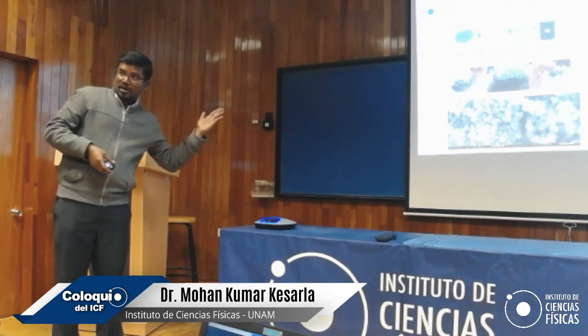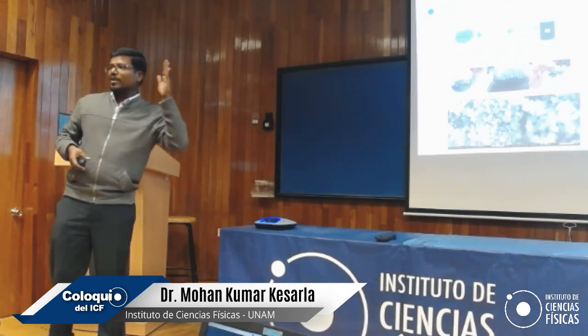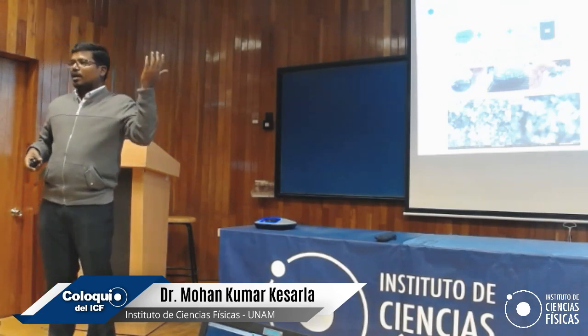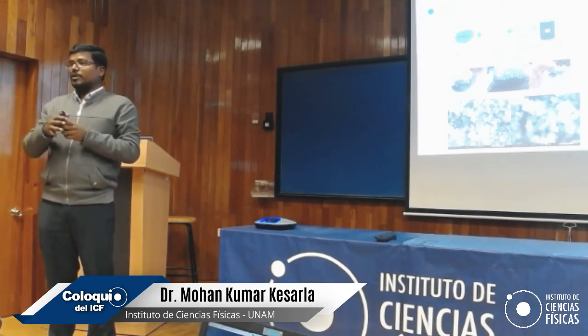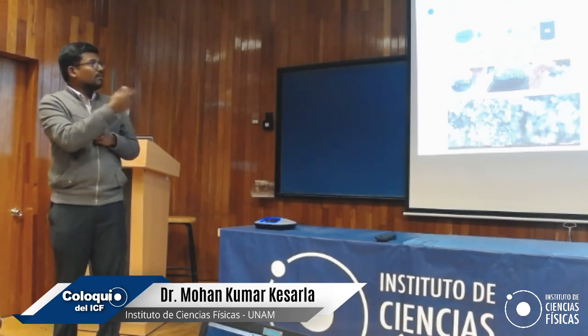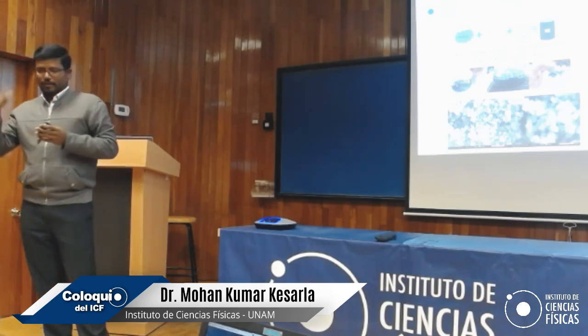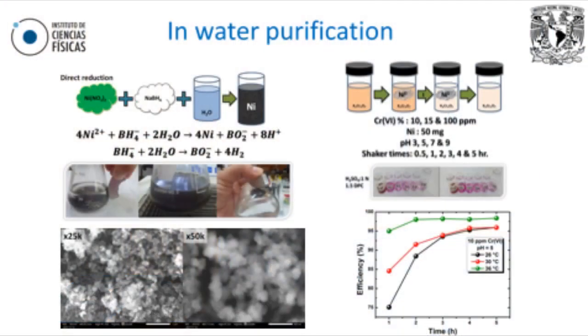And prior to testing this particular zero valent metal, that is zero valent nickel, we just tested zero valent nickel directly for the removal of chromium, which is a pollutant. As I showed in previous slides how we prepared the zero valent iron, in a similar fashion we prepared zero valent nickel using sodium borohydride, and it is magnetically separable. You can see here, you just put a magnet and you can remove the adsorbent, and then we tested the adsorption studies with chromium.